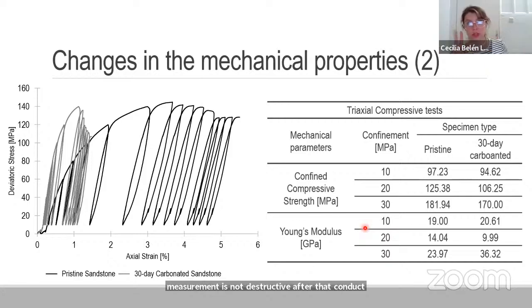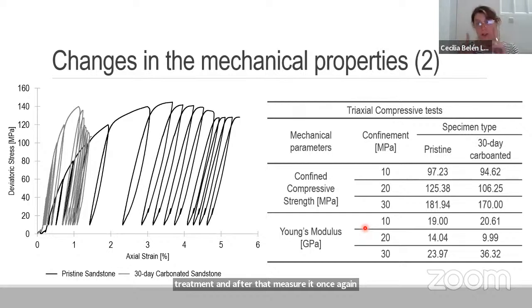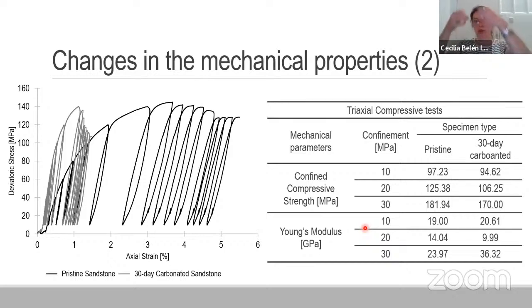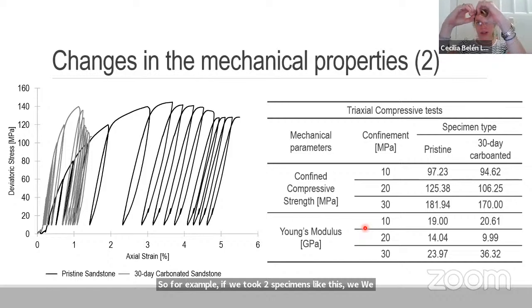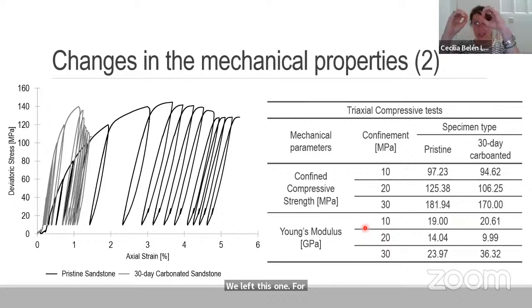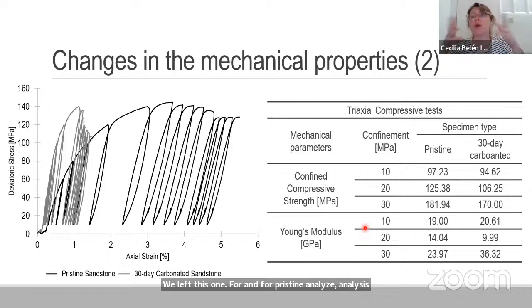Well, I have to mention two things. On the one hand, you are right about the heterogeneity, but we tried to obtain specimens that we called twin specimens. For example, if we took two specimens from our sample, we left one for pristine analysis, and the other we carbonated. So we considered that there wasn't heterogeneity because they were basically the same in some way.